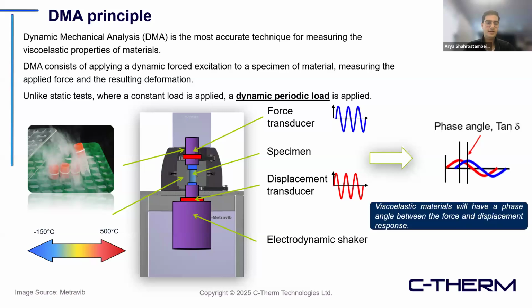So basically, the way that a DMA instrument works is that the DMA consists of applying a dynamic force excitation to a specimen of the material, measuring the applied force and the resulting deformation. So the nature of viscoelasticity of materials after each test shows a phase lag between the force or displacement applied on the sample and the response recorded. And this delay is called phase angle. And this is very important with viscoelastic properties, and it plays a key role here.